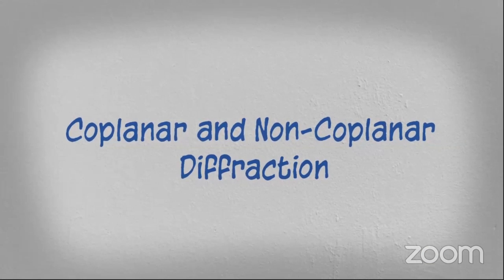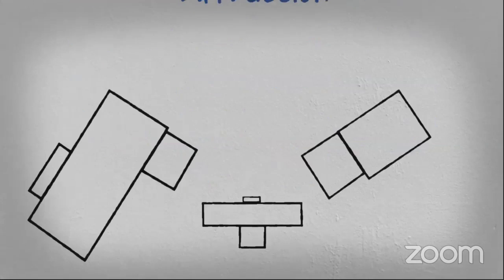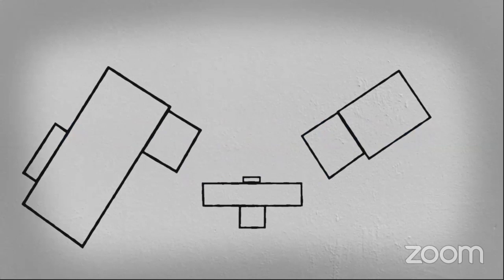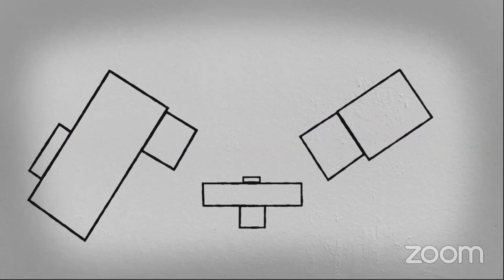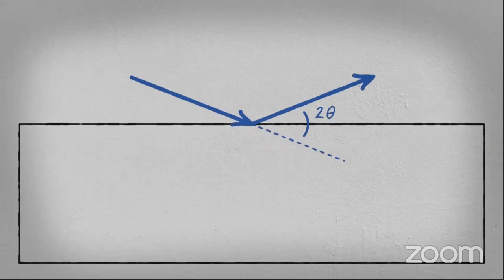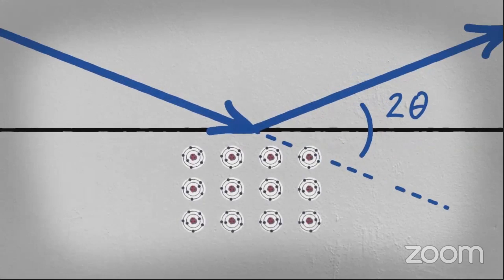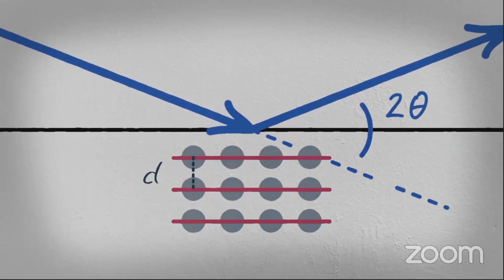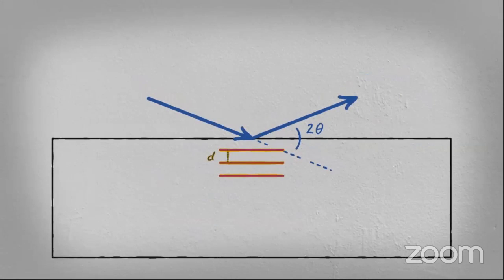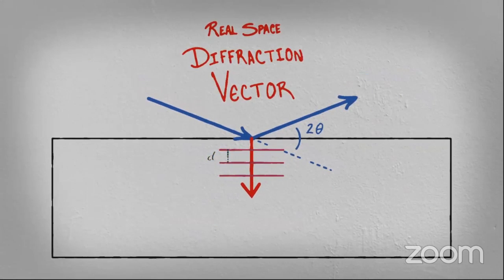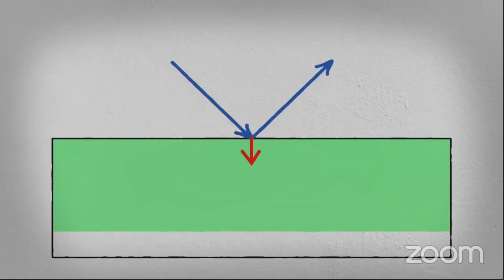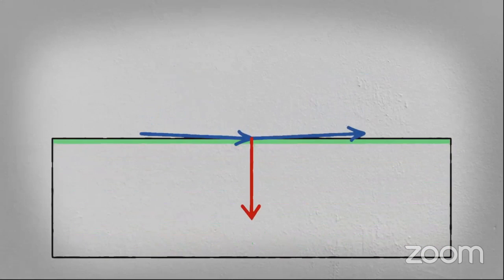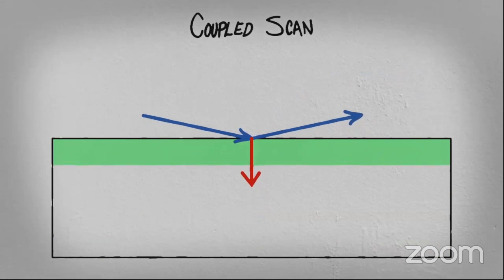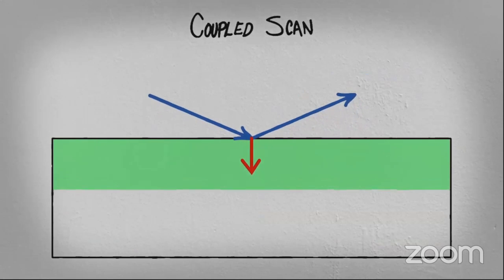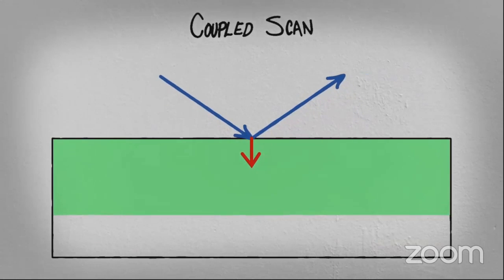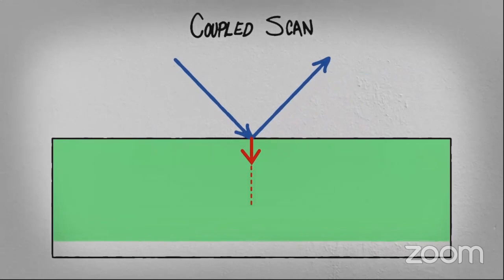Coplanar and non-coplanar diffraction. An X-ray diffraction experiment consists of a source, a sample, and a detector. The angle between the incident and diffracted beams set the atomic distance and direction being analyzed. This distance and direction define the diffraction vector. Additionally, the angle of incidence is tied to the depth of penetration. In a coupled scan experiment, the distance and penetration will change throughout the scan. However, the direction being measured will not change.